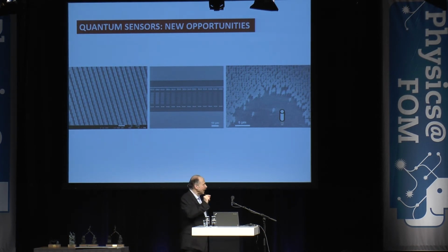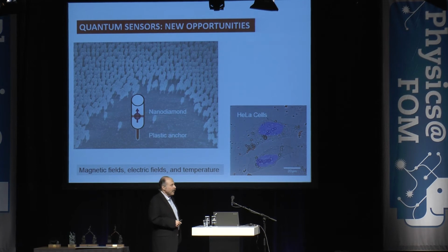And the idea is that each of these structures have either 1, 2, or 3 quantum states in them. You release them by putting them in an ultrasonic cleaner, effectively, get them in solution, pour them through filter paper, and you end up with these little quantum probes, each spin engineered with a couple of quantum states. And you could take these probes and use them. So there's a blow-up of them. And so what are people doing with these types of probes? Well, a group in Australia has done some beautiful measurements shown in the bottom right, where they've actually put quantum probes inside live cells, these HeLa cells, and used them to measure electromagnetic fields in the cell.